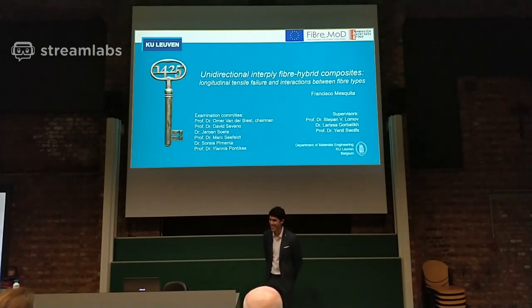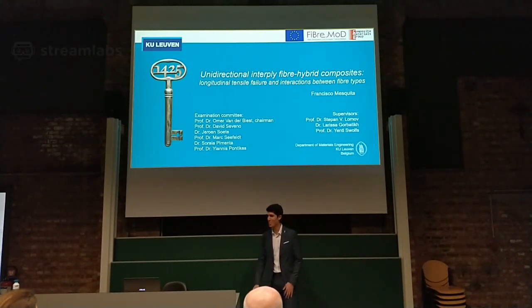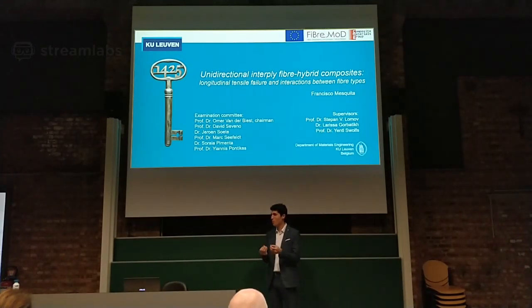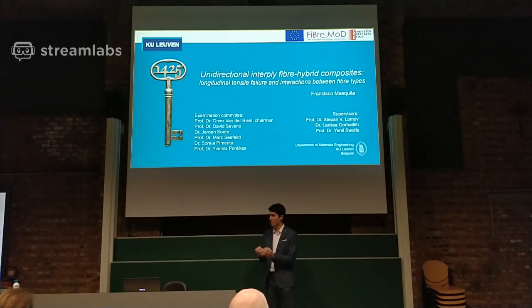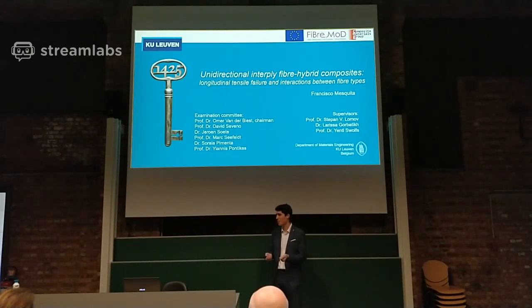Yes, for sure. Actually, I think it was Fabio that asked me that question at home the other day. What's the difference? Why do you have a matrix after all? There are different things. If you don't have the matrix, one fiber will break, and all the other fibers will share the load equally, so there will not be these stress concentrations locally. But that's not all. Fibers work very well in tension, but imagine putting compression only on the fibers. That will not work. And maybe not compression purely, but think of bending. If you try to bend fibers, they hold no resistance whatsoever. So you need the composite.